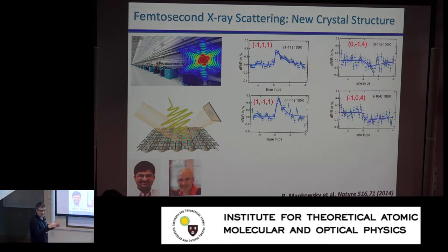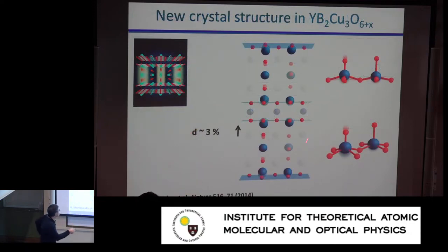So we measured a bunch of peaks and we reconstructed, based on the elementary theory of nonlinear phonons, a transient crystal structure of the state, and we discussed whether this new crystal structure may or may not be the source of a higher temperature superconductor, which would then be very interesting because you could convince a chemist to try to grow a structure like this, and then you'd be making a room temperature superconductor.